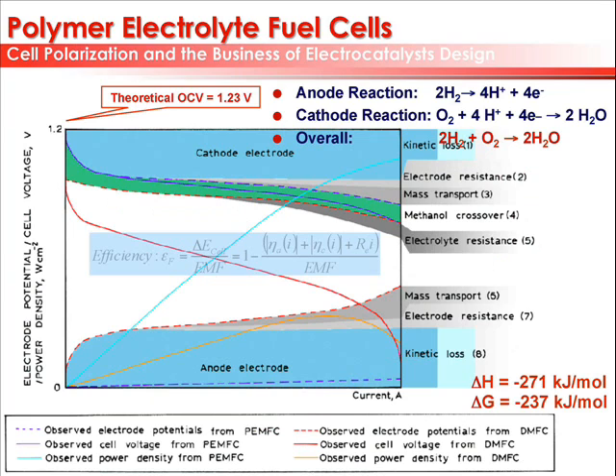Fuel cells are characterized by their losses. And for some reason, electrochemists, being practically optimistic people, call their losses overpotential. If they were realistic, they would call it underpotential, I guess. But the overpotential is a way of expressing how much you lose from the thermodynamically given value. If you are trying to oxidize hydrogen with respect to oxygen electrochemically, your thermodynamically given value comes from God through his prophet, Josiah Willard Gibbs. You cannot get a larger value than 1.23. Everything else that you get at any given current is a loss.